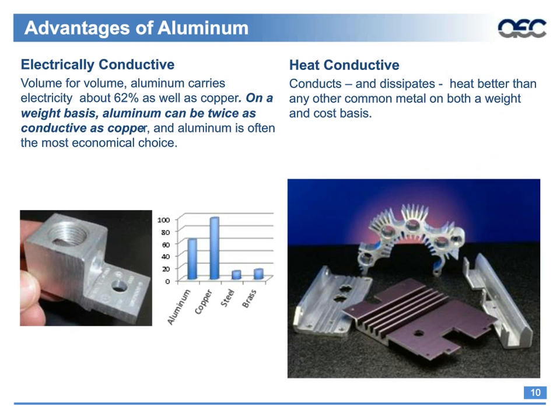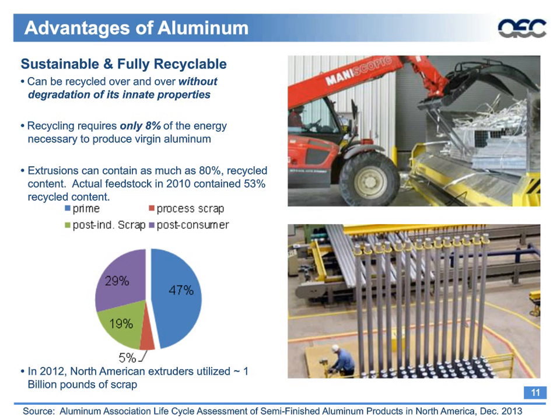Aluminum is also very electrically conductive. On a volume basis, it's about 62% as conductive as copper, but on a weight basis, it's actually twice as conductive. So it's a terrific material and very economical, and you'll see some of the other advantages that make it so in a few minutes. It's also very good at conducting and dissipating heat better than most other common materials, which makes it ideal for many, many applications.